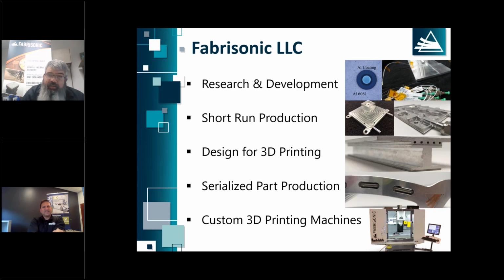Yeah, actually, our number one application right now is in electrification. We can combine aluminum, copper, and nickel steels, stainless steels, all in a foil type arrangement. And you start looking at a lot of the electrification devices, especially some of the high current devices, being able to get multiple metals very quickly into a foil-based laminate has a lot of advantages for manufacturing of these electrification devices, as well as thermally. A lot of work taking high power electrical systems and building thermal devices around them. So starting with a pre-existing part and building up thermal materials like copper and aluminum, as well as fin structures around a pre-existing power electronic. A lot of work in that area.